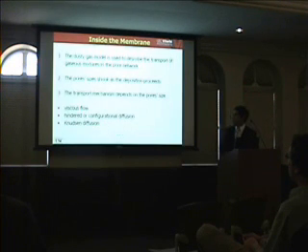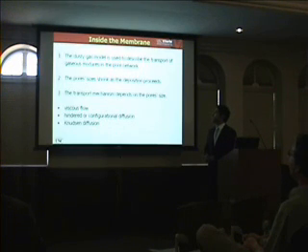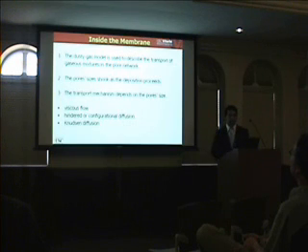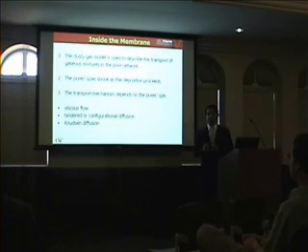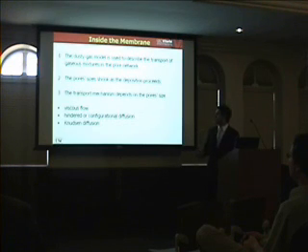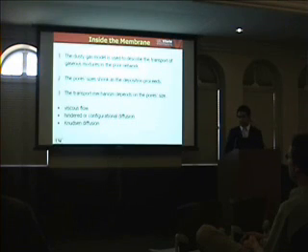So in order to let these things go in, we used the dusty gas model, which is the same as the Maxwell-Stefan equation, and the pores shrink as the deposition continues, and since the pores are shrinking, the pore size varies during the deposition. So for each pore size, you have to use a different mechanism for the transport, including viscous flow for the really big pores, hindered or configurational diffusion, and Knudsen diffusion, and we have to take all these 3 into account.